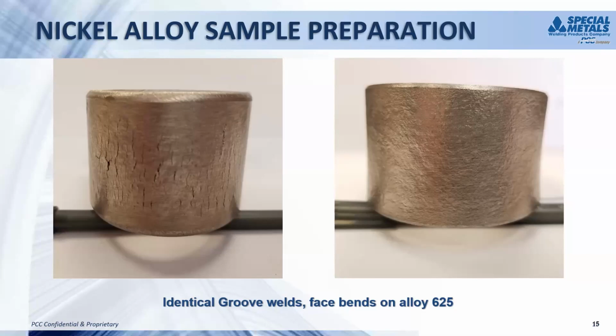The one on the right was the same identical welding conditions. The only difference was the way the sample was prepared. It was machined and lightly ground, and then bent in a wraparound jig, which really didn't have a lot to do with it. But if you have an option, that does tend to work a little better with the nickel alloys.